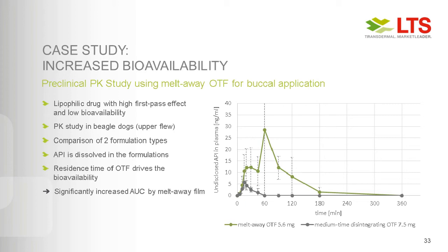So it was a very lipophilic drug, and due to this high first-pass effect, it has a very low bioavailability. So as you can see, it was applied to the beagle dogs, and we compared these two different formulations. In both formulations, the API was simply dissolved, so not dispersed or emulsified, they were dissolved in the film in order to present it immediately in a dissolved form to increase the oral mucosa uptake. The gray curve you can see here in the profile, which was the film which disintegrates faster, so after 10 minutes everything was gone, was loaded with 7.5 milligrams of this API.